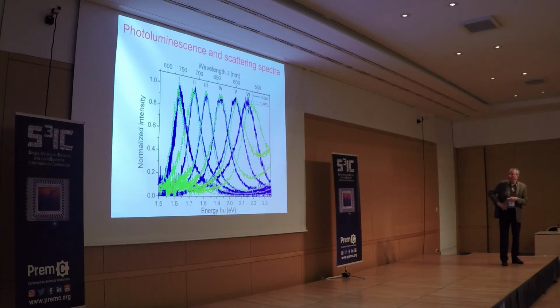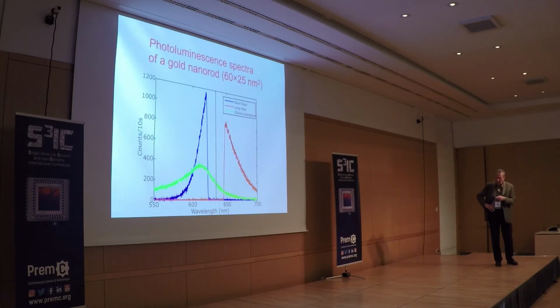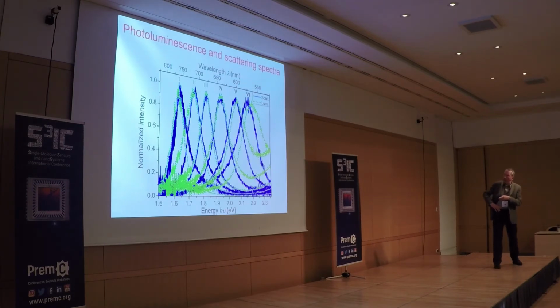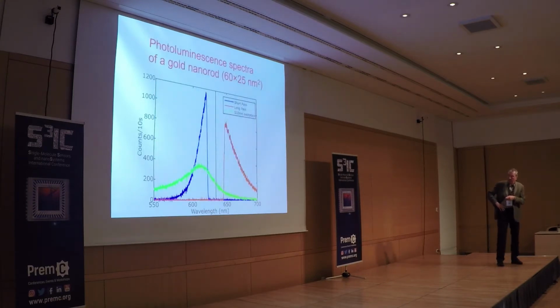All right. So that's what you do. So what you can do here, sorry, I have to go back. What you can do here is excitation at 532, about here. But you can also excite the luminescence with a laser inside the plasmon band. And that's what Achilles has been doing here. So the laser is 633, the helium neon laser, and we excite here. And of course, there are filters to cut the laser light around the photoluminescence. The laser light is much more intense than the photoluminescence.